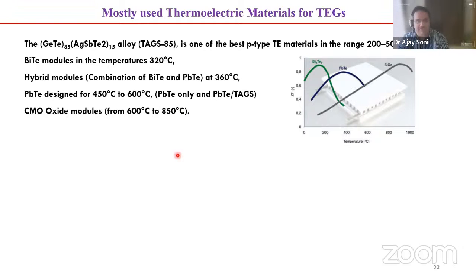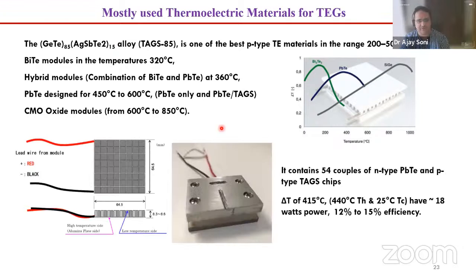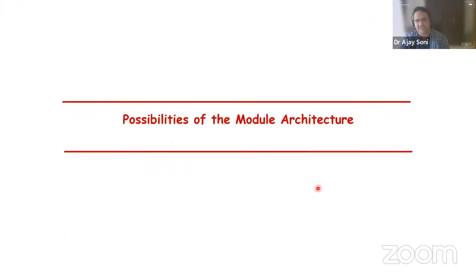All right. So we were talking about the material system, the materials aspect of the thermoelectric module, and you can see there are a few materials which are called the champion materials, like germanium telluride, bismuth telluride, lead telluride, and some of the oxide-based materials, and silicon germanium-based materials, which work in different temperature ranges. So for space applications, mostly the materials which have been used are the silicon germanium based materials, and for room temperature it is the bismuth telluride based material. Which means the material aspects are very important.